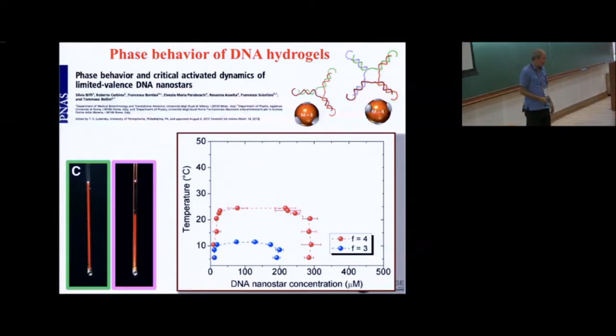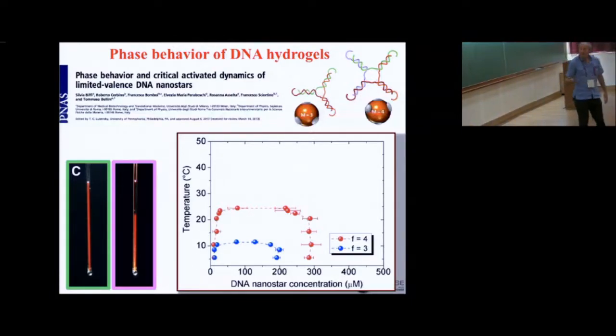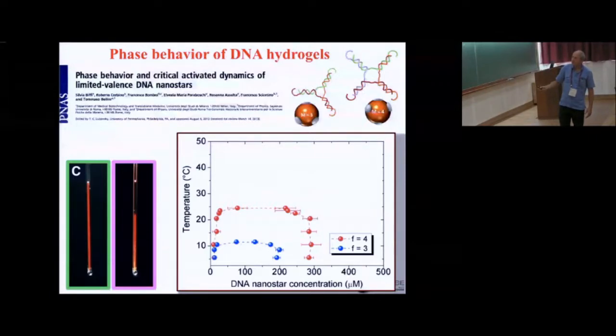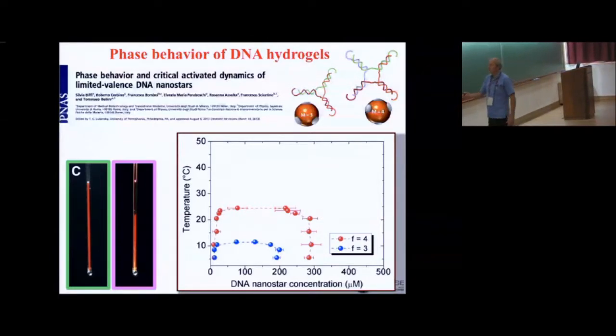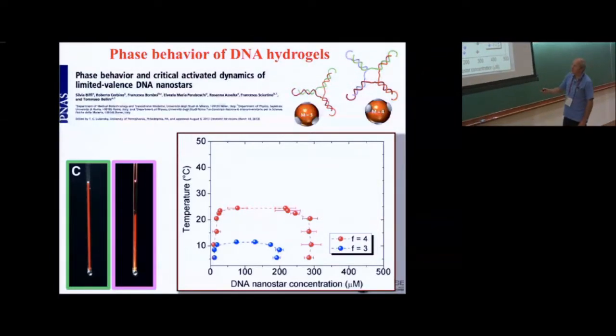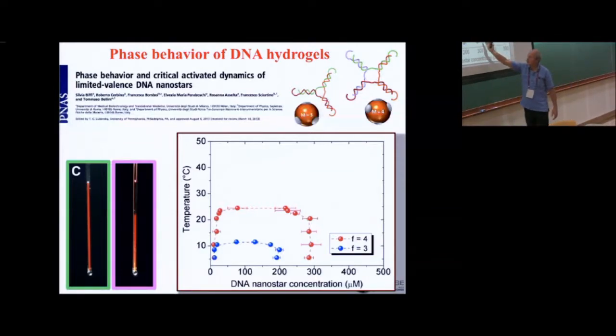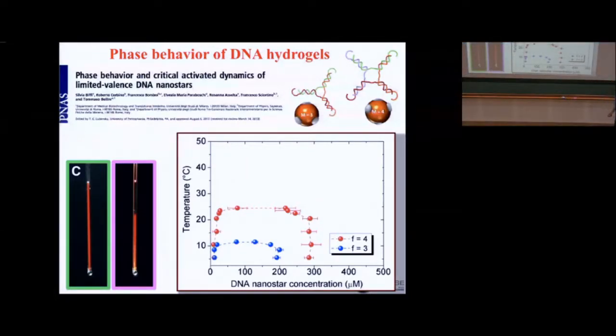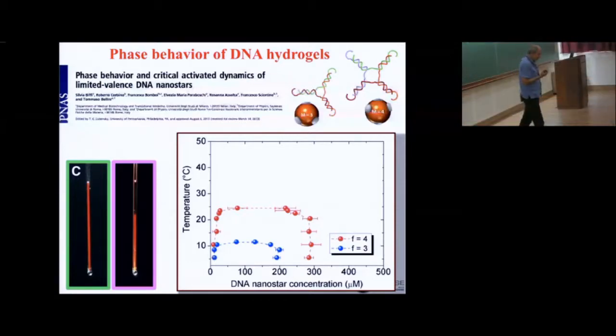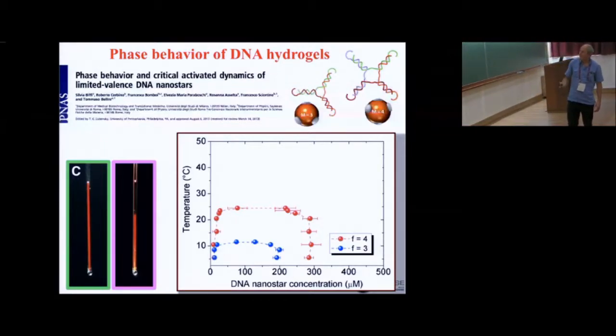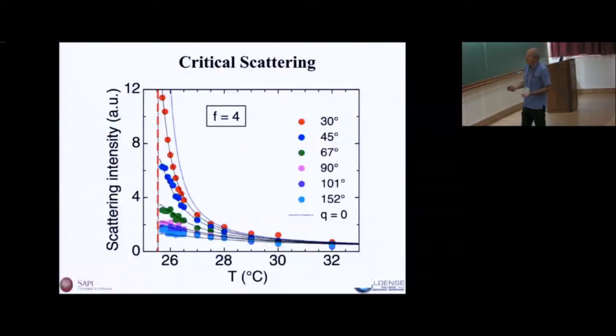You can measure with UV absorbance the amount of DNA, so you can plot the concentration of the DNA in the sample in the gas phase and in the liquid phase, and then you can rebuild the phase diagram. And you see exactly what we have seen in the simulation: the critical temperature goes down, the critical density goes down from here to here, and the density of the liquid coexisting with the gas shifts to the left on decreasing the valence. So this is really the first careful experimental test of this idea that the valence controls the phase diagram. And it is a real phase separation.